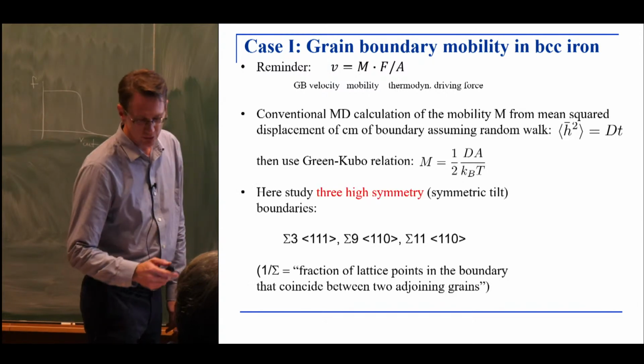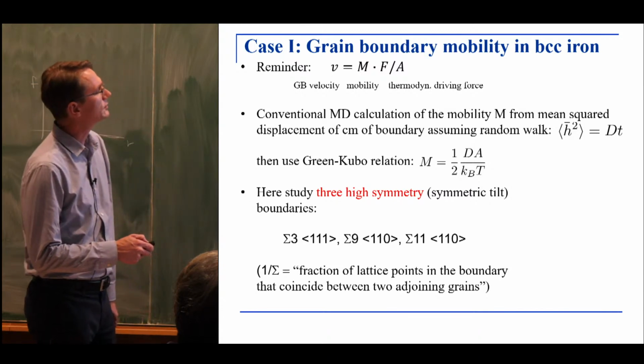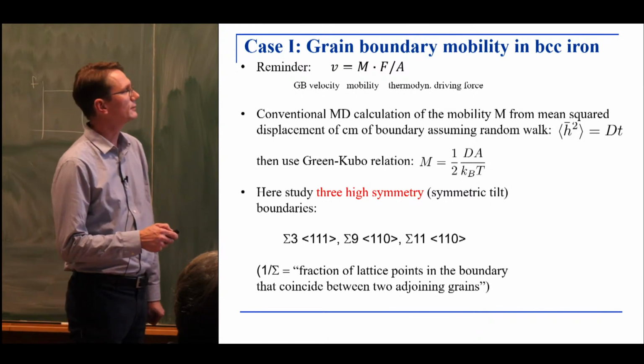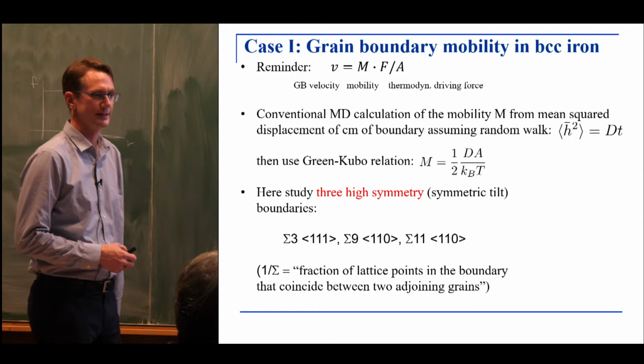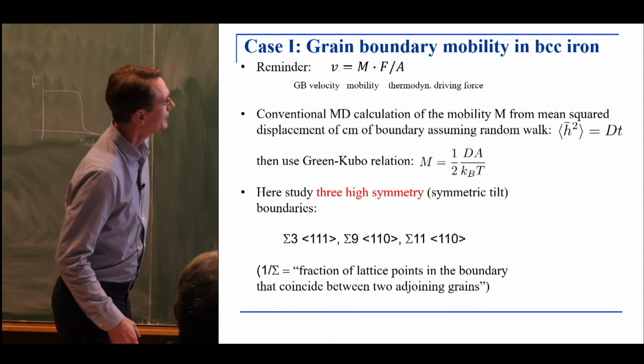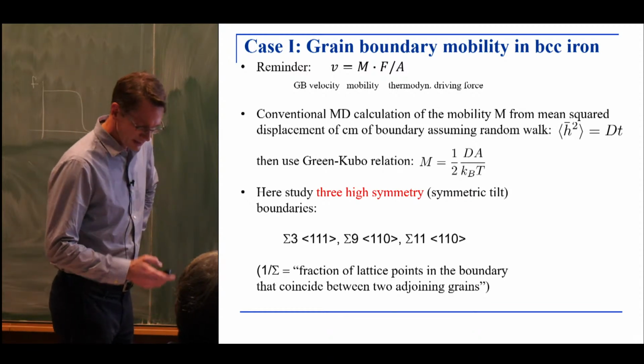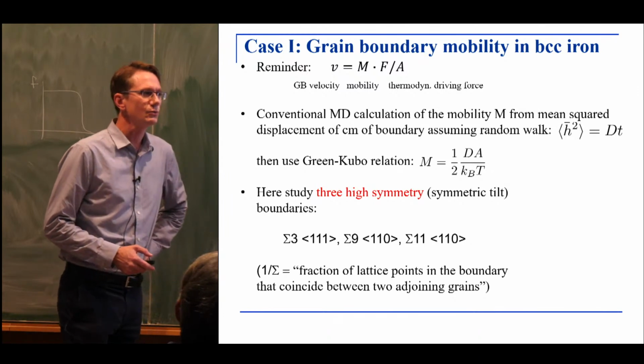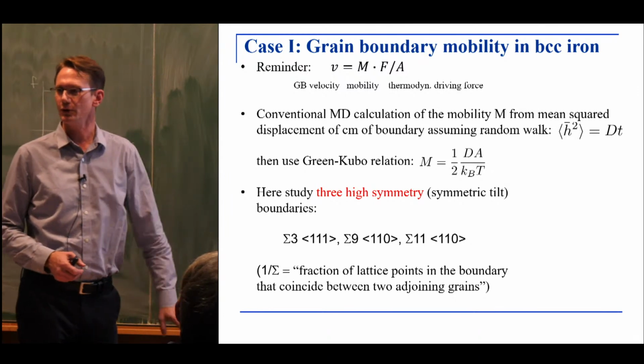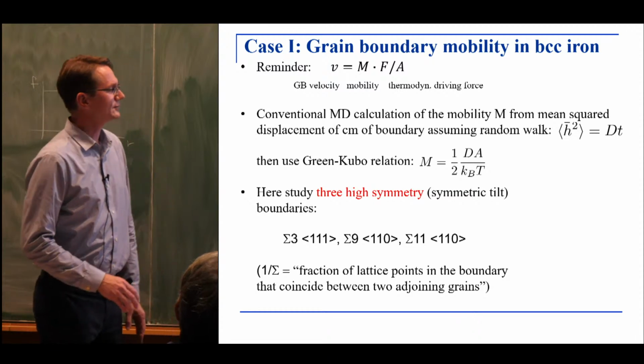All right, that's a standard approach. Now, what we're going to do here is look at three so-called high symmetry boundaries in BCC iron. This is mainly because my collaborators are physical metallurgists, and they want to make steel, so they have to look at iron. But this is actually not terribly important. If you don't know what a sigma 3, 111 boundary is, don't worry. It's not a detail that's terribly important.